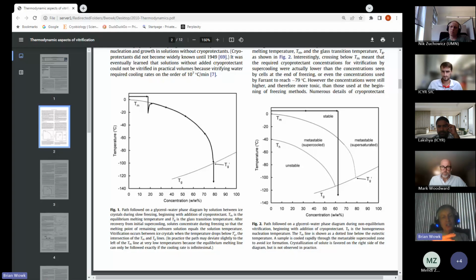It changes so fast that it doesn't really matter whether you set that critical threshold at 5 nanometers or 20 nanometers. It's going to probably make less than a degree difference in this TH value anyway. But it comes from this Gibbs-Thomson equation, and that's where TH comes from in pure water.